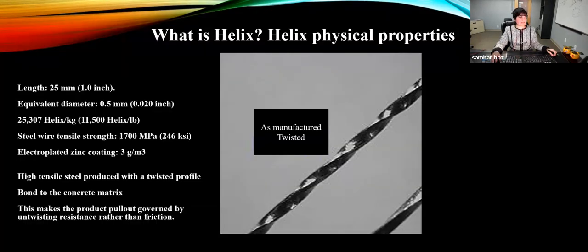So what is Helix? Helix physical properties. Helix is 25 millimeter long or 1 inch. Equivalent diameter is 0.5 millimeter or 0.02 inch. Due to the size of it, you have more than 25,000 helix per kg or 11,500 helix per pound. The actual material, the steel wire tensile strength is 1,700 MPa or 246 KSI, which is close enough to what we use in post-tension cables.